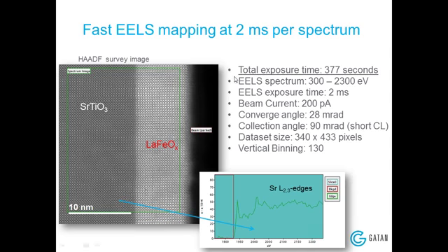The first data were taken across this interface, and the beam was scanned over a pretty large region across the interface, along the interface. You can see that, according to this image, the interface looks nice and smooth, and the area scan is pretty big. It's several nanometers. The entire area was covered at atomic level in just over 6 minutes, and each spectrum was acquired with an exposure time of 2 milliseconds. Even with such a short exposure time,